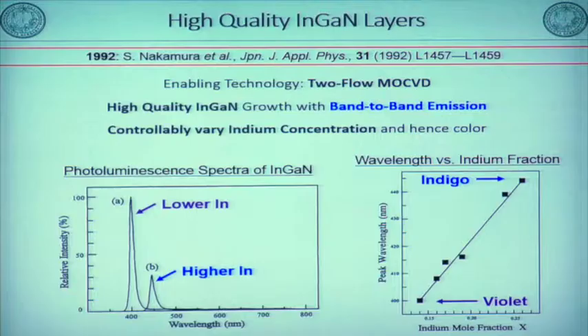But I told you, using the two-flow MOCVD, in our group we got very strong band-to-band emission for blue and violet, also green, in 92. I told you the two-flow MOCVD is the best reactor, so we could make a big breakthrough for the active layer. We got very strong band-to-band emission using indium gallium nitride for the first time in 92. So now we can make a double heterostructure.